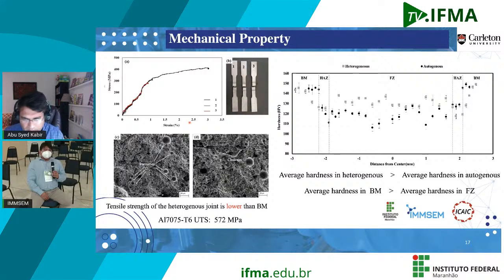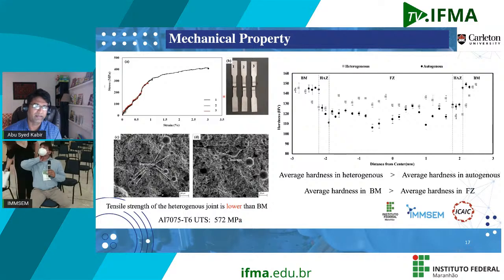Now, we performed some mechanical property tests as well, and first of all, we couldn't test the autogenous welds because of the large solidification cracks that we have, but we tested the heterogeneous welds. We found the mechanical property is, in some cases, good, in some cases it's not that bad, not that good, and they all failed in the fusion zone. But the main idea is that 7075 is stronger. 7075 has an ultimate tensile strength of 572 megapascal, but what we got at maximum is approximately 400 megapascal.